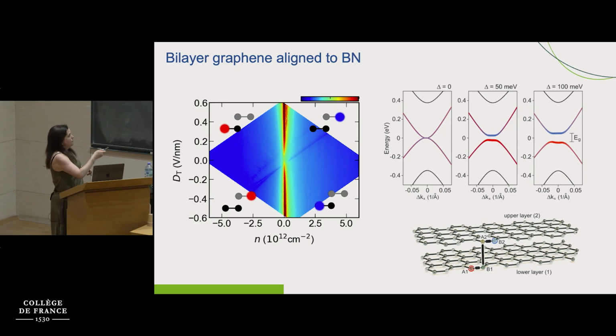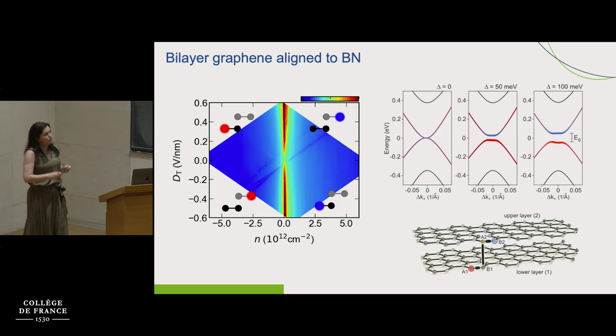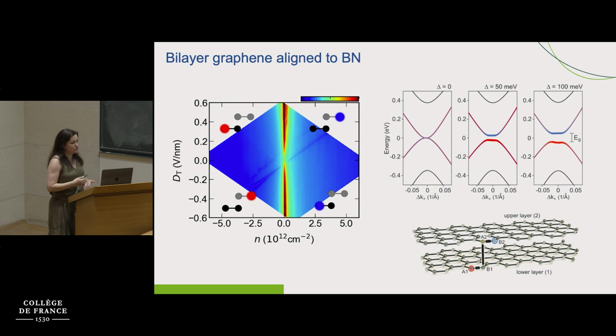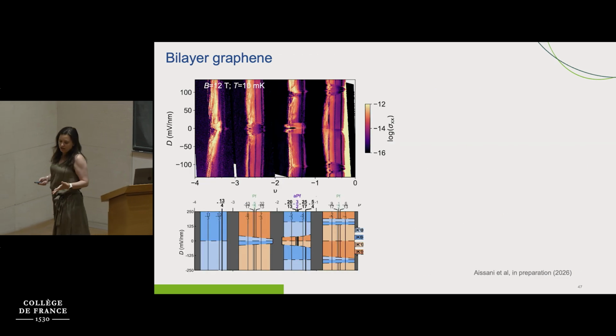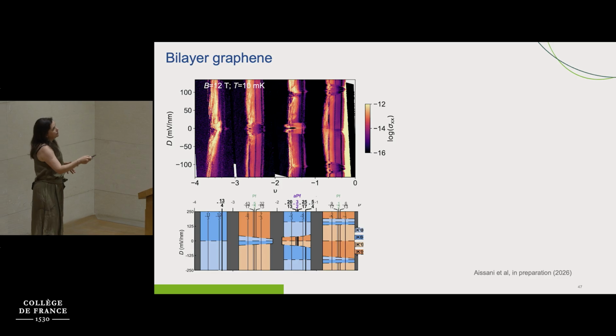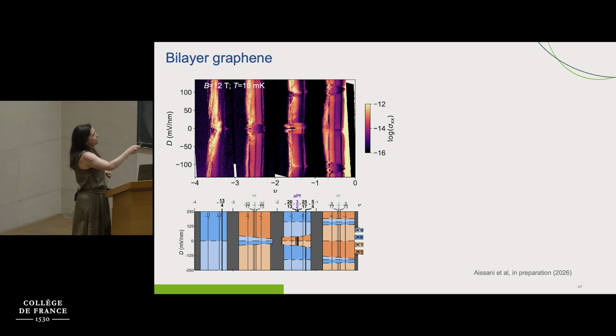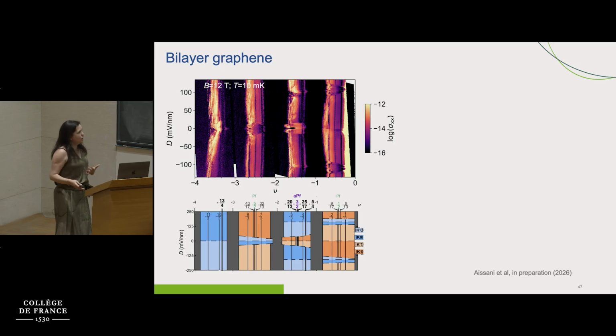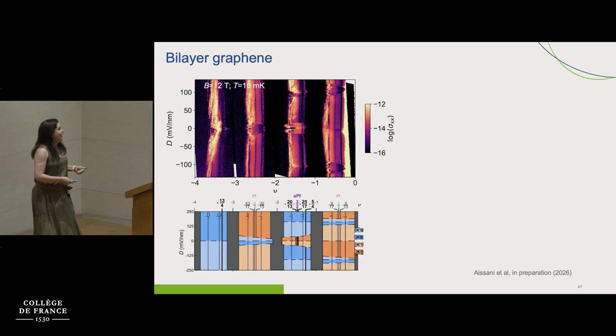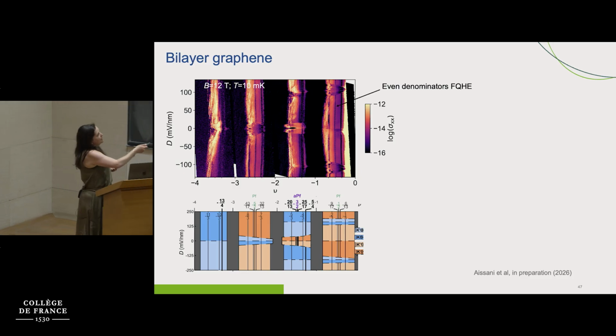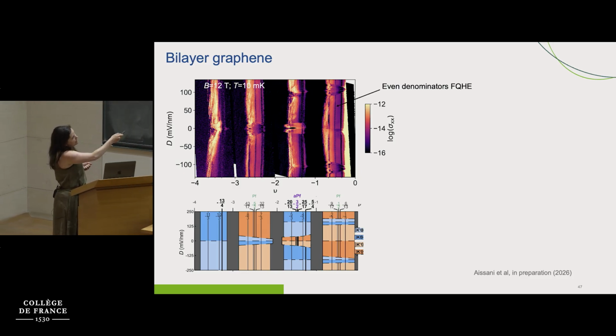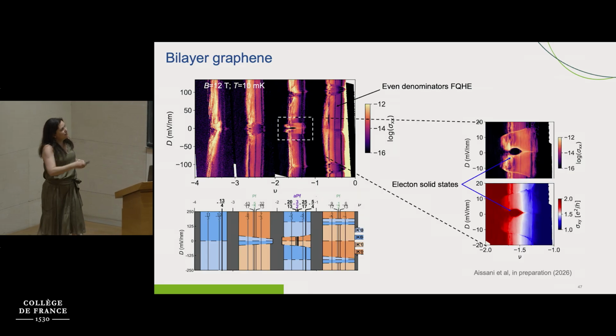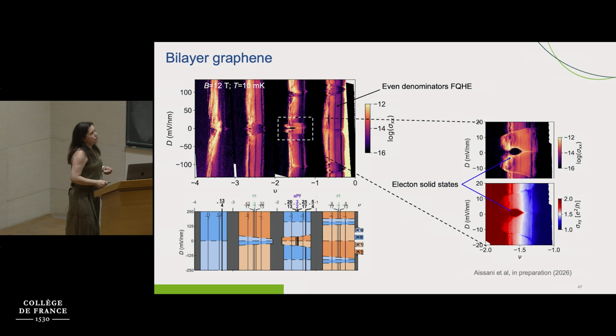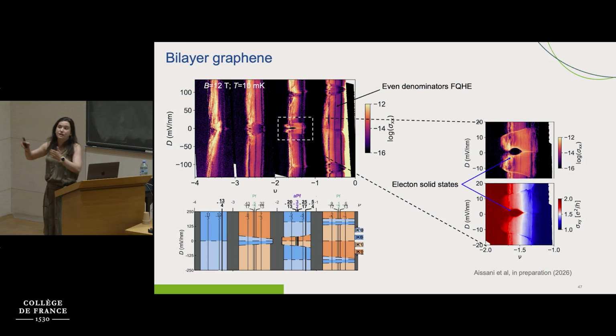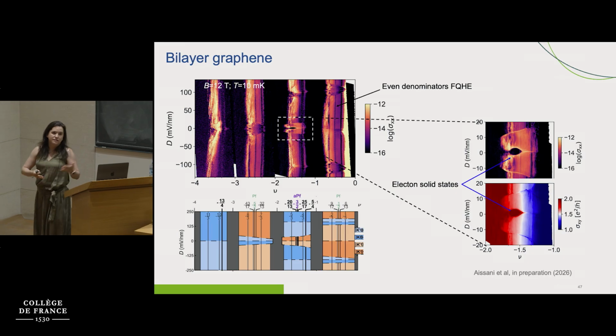Okay? So where are we? Bilayer graphene. We have an energy gap, we have a parabolic energy dispersion, which also means that our interactions should be larger. And in fact, they are. When you look at what happens when you apply a magnetic field in the lowest Landau level, you can see that now this lowest Landau level has a combination of orbitals, spins, Landau level index, etc. But you can also see the presence of very prominent and very clear even denominators fractional quantum Hall states. And even if you have a look here, you can see the formation of electron solids, which means that we have recreated already in bilayer the same things as in gallium arsenide.